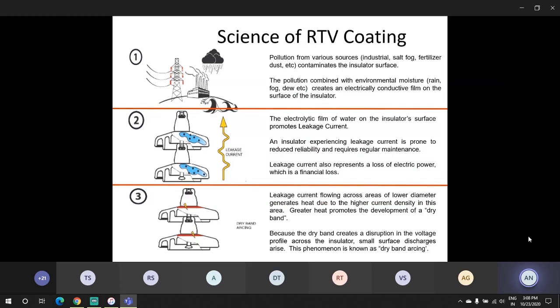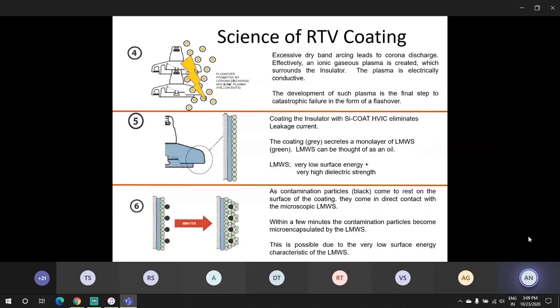This electrolytic film on the insulator promotes leakage current and later develops into dry band arcing, which necessitates cleaning or hot or cold line washing on a regular basis to prevent this phenomenon. And if it is not attended to, it leads to a flashover and interruption, the failure of the insulators.